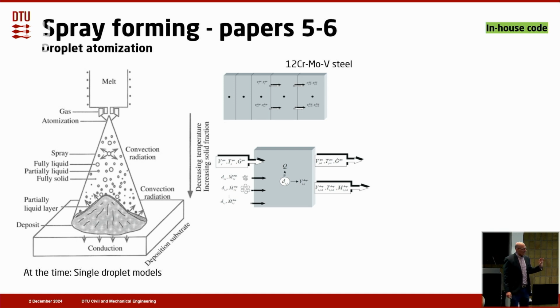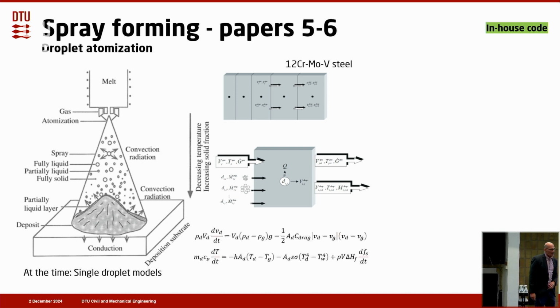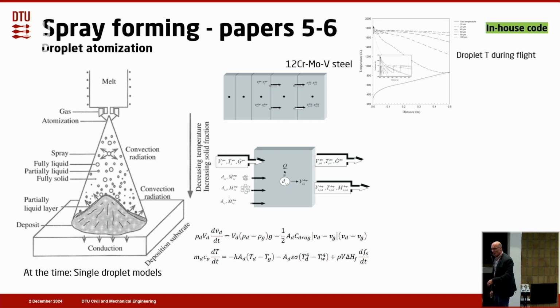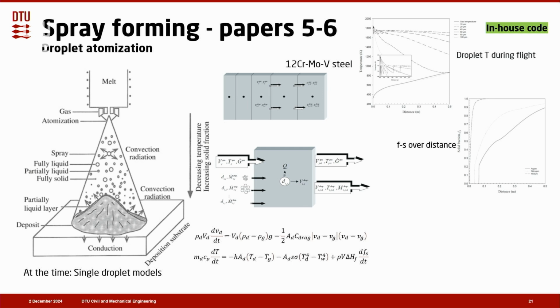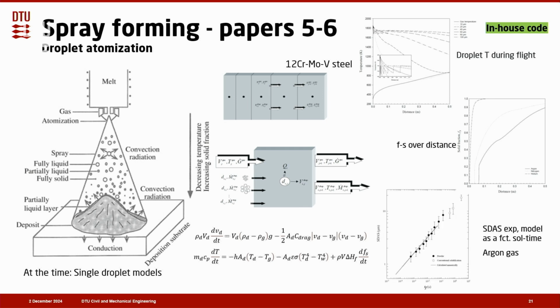And then we turn it around, and then you see that it was a balance between the droplets and the enveloping gas, where we solved the one-dimensional momentum equation as well as the energy equation for the droplets. This is what you see here. And with this, we could predict the temperature during flight, solid fraction over distance, as well as compare with experiments from secondary dendrite arm spacing. So this model was just the atomization model.